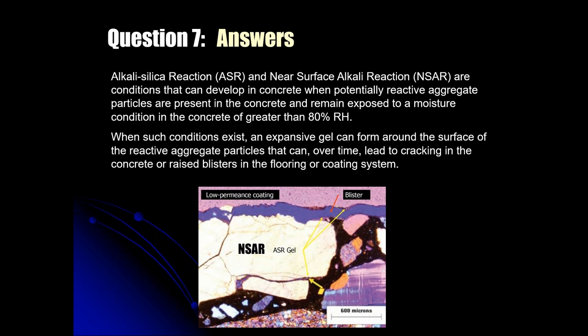ASR is a very slow growing cancer, where NSAR is a cancer that can develop in a much shorter period of time. Both, however, require that in the concrete mixture itself, and this can be in the coarse or fine aggregate, there are particles that really should not be in the mixture. And these particles are potentially reactive, and reactive in a saturated, high alkaline environment, which an unprotected concrete slab on ground, unprotected from below, can easily become.